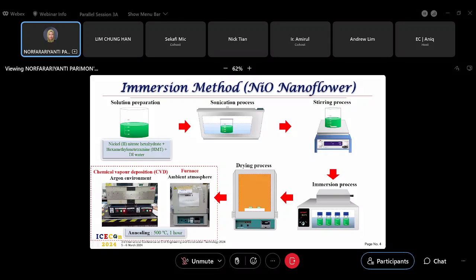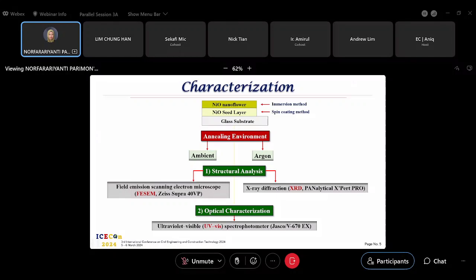In the argon environment, we anneal or calcine in the chemical vapor deposition system, and with the ambient atmosphere, we anneal the sample in the common furnace. The annealing temperature is 500 degrees C for 1 hour. For the characterization of the two samples, we just focus on the structural analysis and optical characterization, so maybe further improvement or characterization needs to be done other than the structural and optical. For the structural, we analyze using FESEM and XRD, and the optical characterization is using a UV-Vis spectrophotometer.